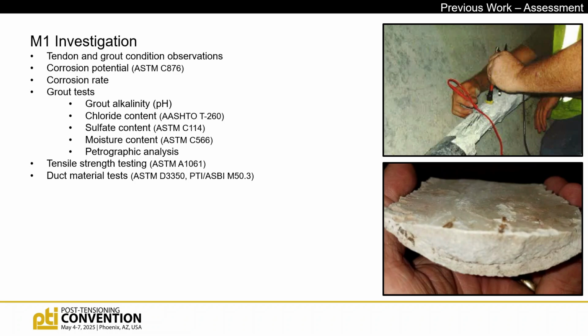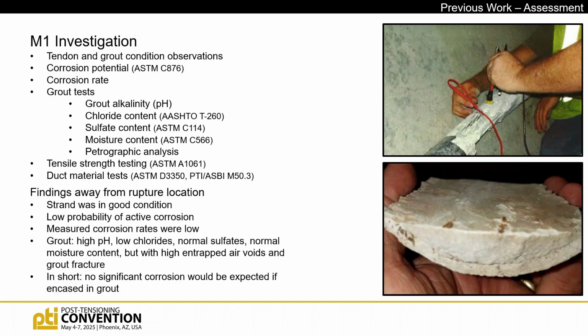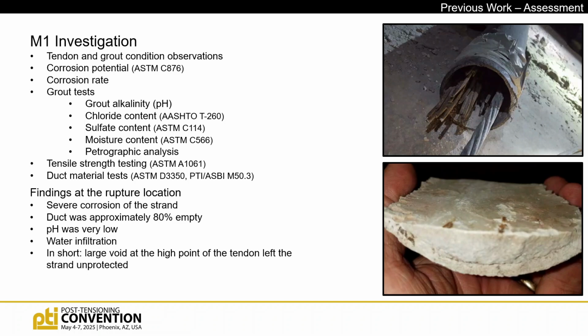So obviously South Carolina wanted to know what happened and what's the condition of all the rest of the bridges. So looking first at the M1 tendon, that's the one that failed first. We did, of course, visual observations, corrosion potential, corrosion rate, a lot of stuff that Travis talked about, all that battery of grout tests, and then material testing for both the duct and for the tendon. And we found, away from the rupture location, the strand was in actually pretty good condition. The grout itself wasn't perfect by any means, but it was still a high pH grout, and it was protecting the tendon as intended. Very different story at the rupture location.